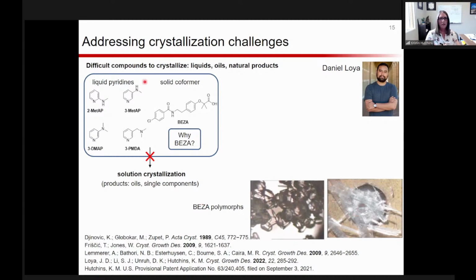And so rather than just quitting and saying that this didn't work, we decided, well, there are a lot of molecules that present difficulties with crystallization, especially those that are liquids or oils. So can we use mechanochemistry to actually get crystallization when solution methods just aren't effective? And we stuck with the bezafibrate because, again, it would be really easy to identify if bezafibrate was crystallizing by itself, because those forms are so easily identifiable. And that would tell us if it was working or not.